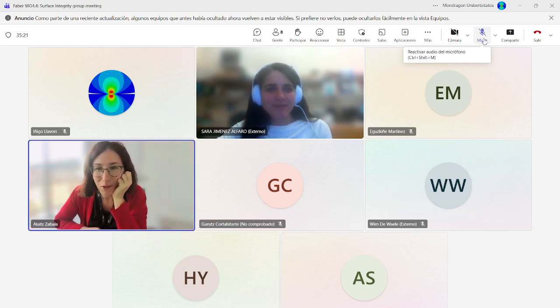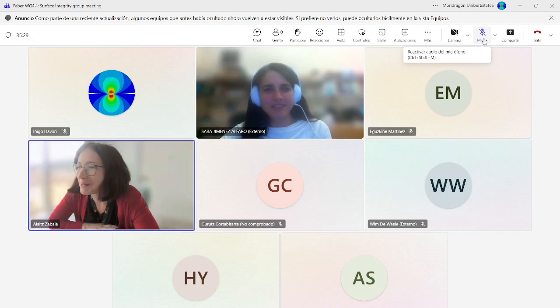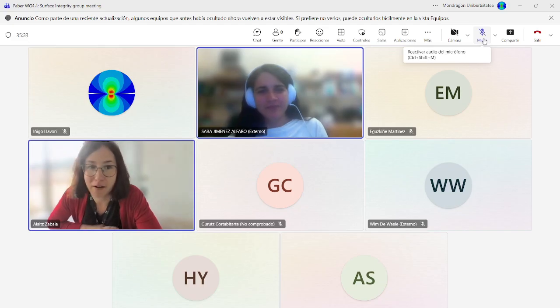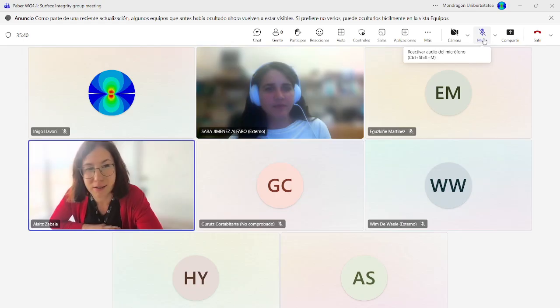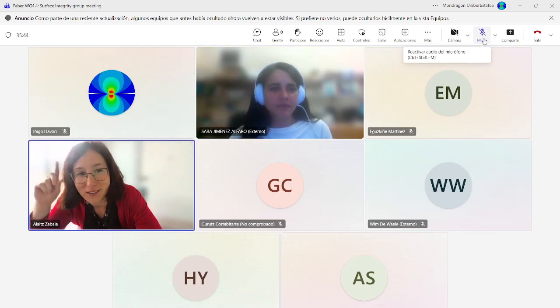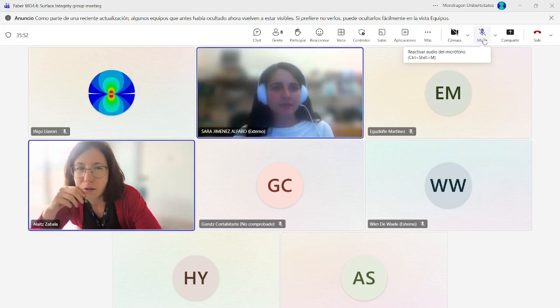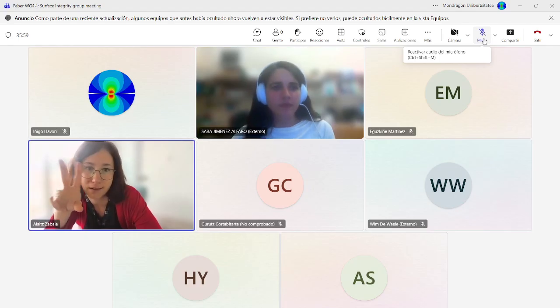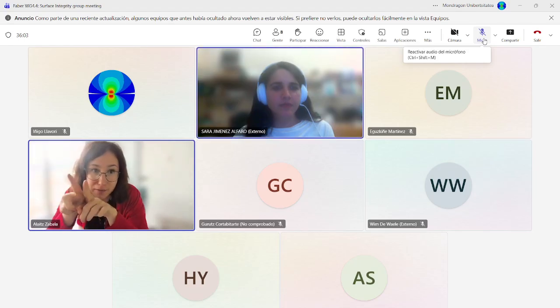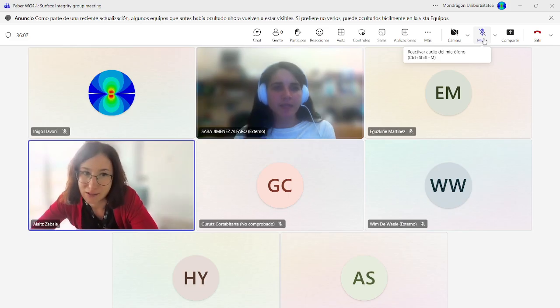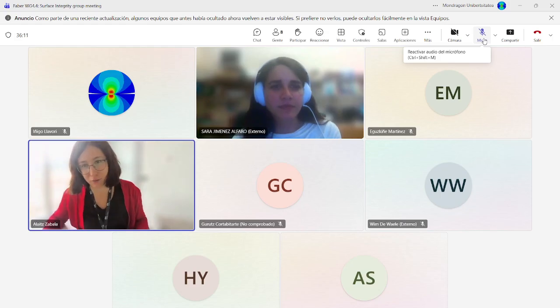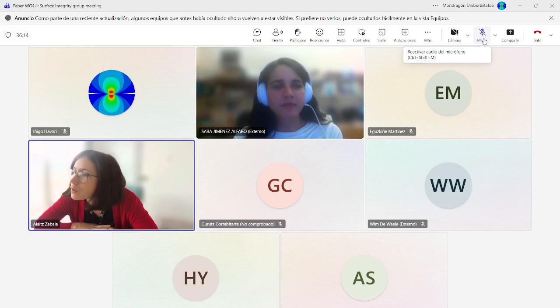So super interesting, Sara. Thank you for such nice work. Very well explained, you're a really good speaker. It's a very clever way to describe the roughness, right? Because you take both the height and lateral description of the roughness. At first, when we spoke at the Congress, I understood that you were using Rq, and I was thinking that using only height is not enough, because we know that depending on the lateral resolution, you will have different angles in the valleys, which is the critical part. So now I can see that the lateral correlation length is a kind of fixing this, representing this, which is great.